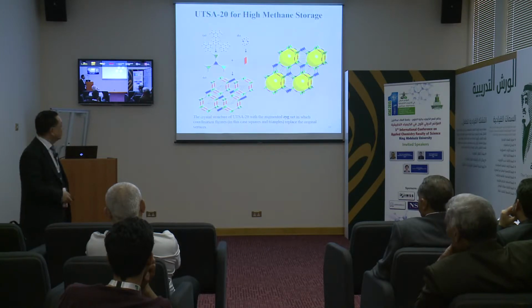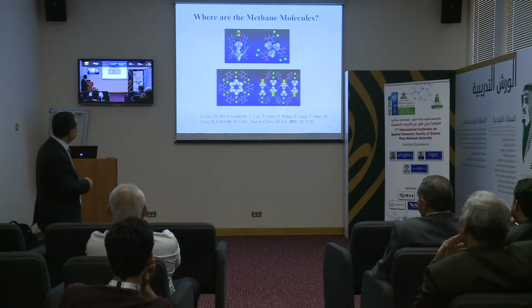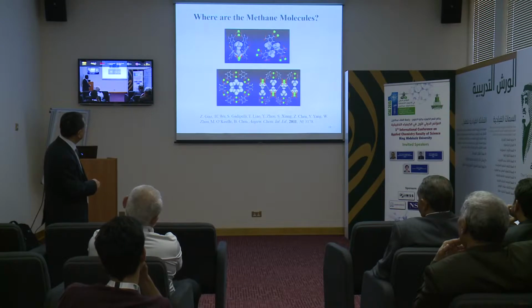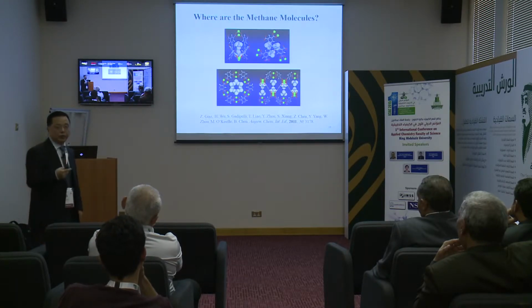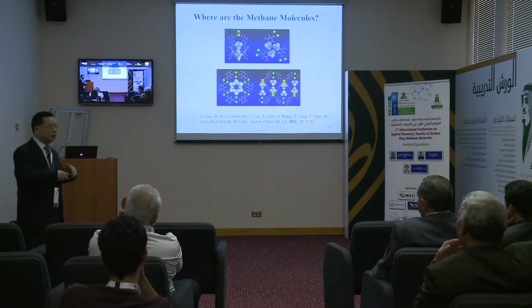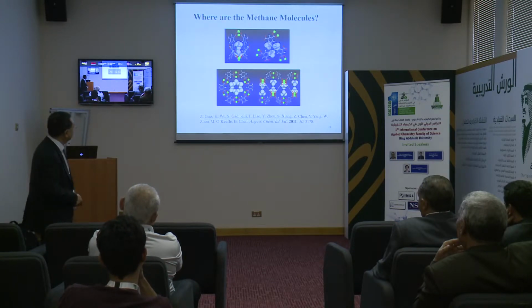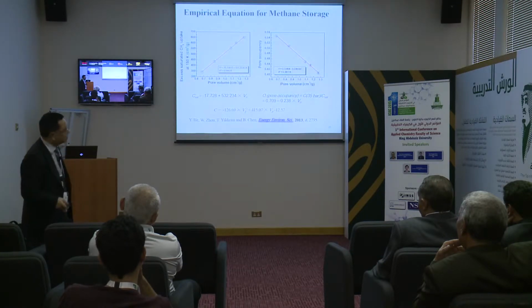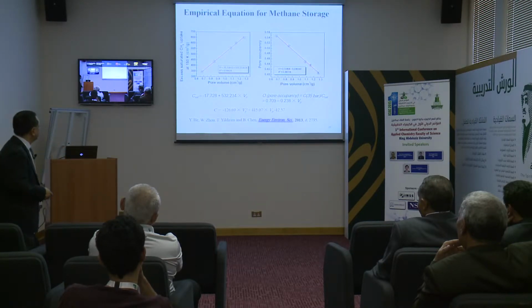Furthermore, this pore surface, this pore cage, is suitable. So we are showing here that a small cage can capture 3 methane molecules, and each open metal site can bind one methane molecule. So overall, this material can store a high density of methane. So this work has been optioned, the patents are optioned to multinational companies.